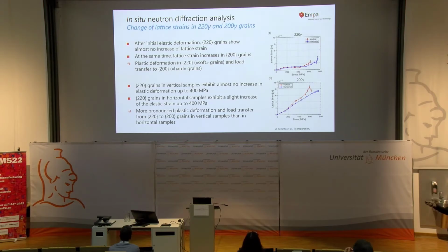Looking at the differences between vertical and horizontal, you can also see that there's more activity in the vertical samples, because here the red curve is really flat, whereas the blue curve slightly increases. And here you see that the load transfer to the 200 is also much more pronounced. So in other words, more pronounced plastic deformation, more pronounced slip activity in the 220, and we have this load